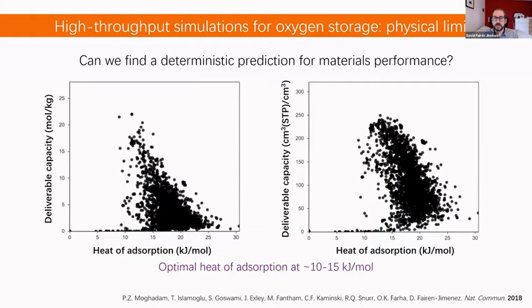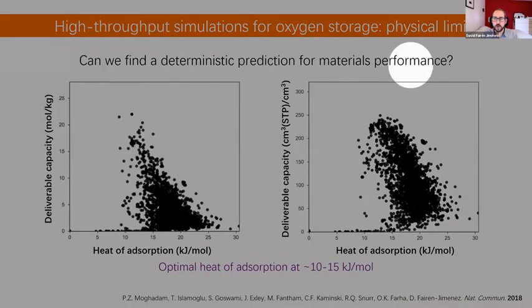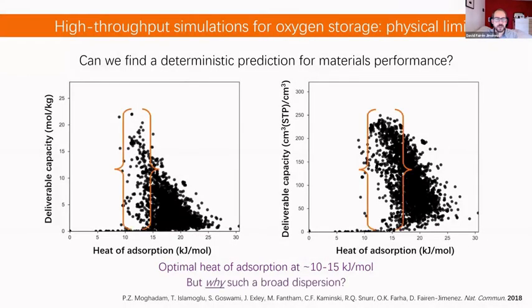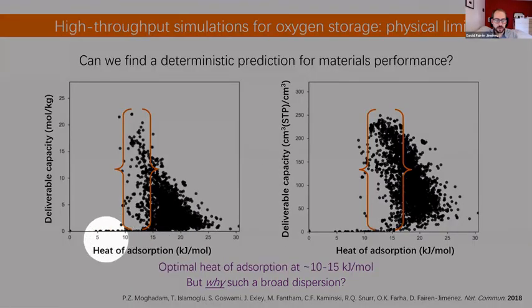This is another example that we published a few years ago. That was for oxygen storage, and this is the capacity of oxygen that we can deliver when we store it at high pressure. This is gravimetric, per unit of mass, and per unit of volume. And you can say the best materials are the ones with this heat of adsorption, which is related to the interaction of the oxygen and the MOFs. Obviously, there are some problems with these kinds of statements, because at this optimal interaction we have materials performing extremely well and materials performing really poorly.